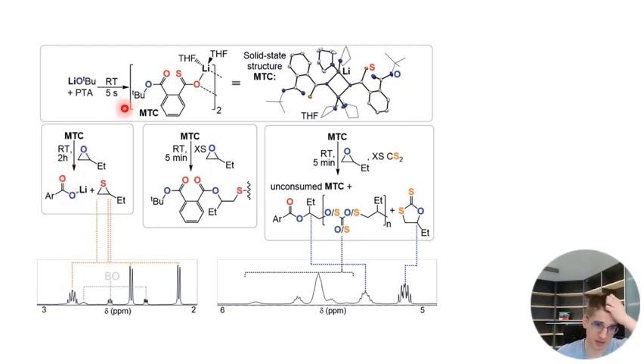How does this rearrangement happen? Or how do these species likely form? It's by the oxygen ring opening the epoxide. Then again, you have an alkoxide next to a thioester that then exchanges to a thiolate next to an ester, and this then eliminates the thiirane. But essentially, the sulfur gets shuffled from a thioester into a thiirane. That then proved well. This exchange seemed to be also reproducible in small molecule reactions and seemed likely.